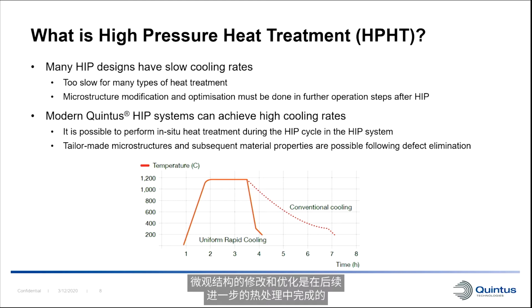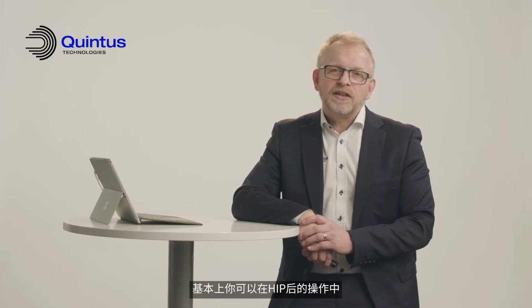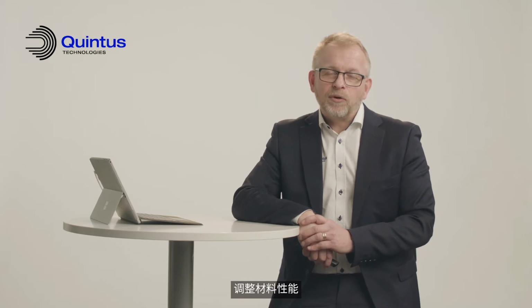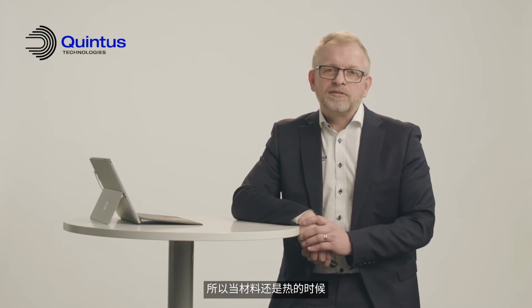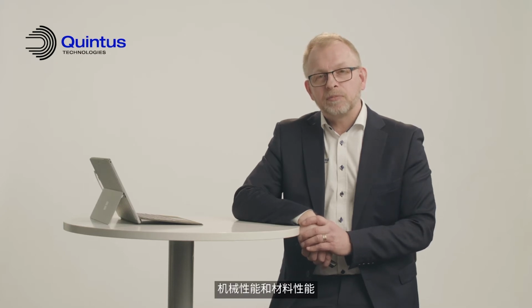Microstructure modification and optimization was done later on by heat treatment in further operations. Modern Quintus HIP systems can achieve high cooling rates. And this means that basically you can adjust the material properties and the metallurgy of the material in the one operation after HIP. So whilst the material is hot, you're just steering the cooling of the material to achieve the right mechanical properties and material properties.